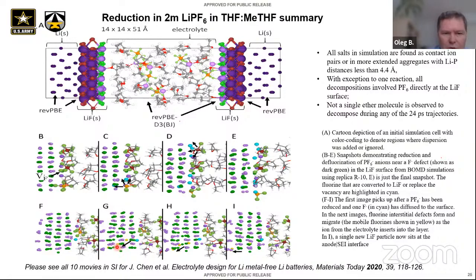The 2nd one also starts moving, and as it enters the 2nd, it's a very correlated event for the fluorine diffusion, sort of similar to what Yifei Mo was describing a couple years ago in Nature Communications papers, that the barrier for the lithium transport simultaneously in many of the solid electrolytes could be lower if all of them move at the same or in a coordinated way. So we think that that could be also the case here.